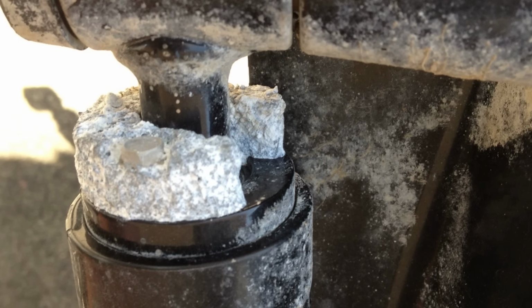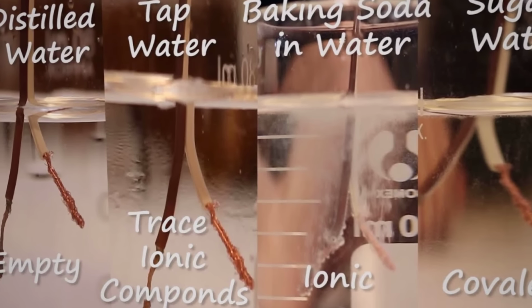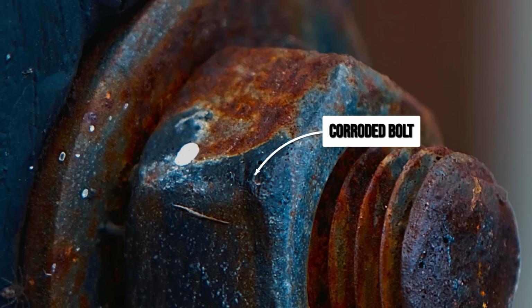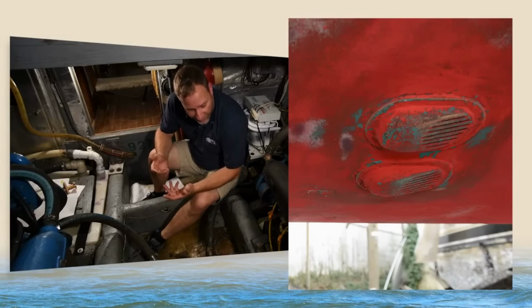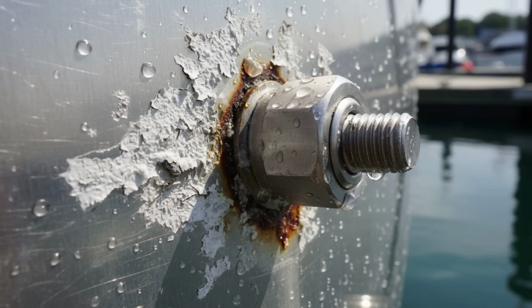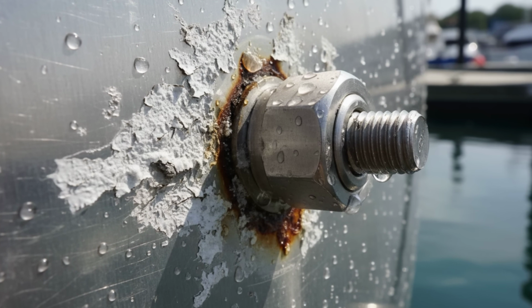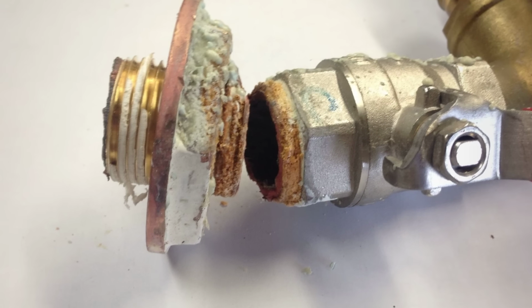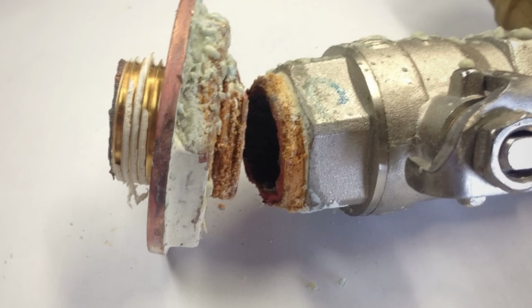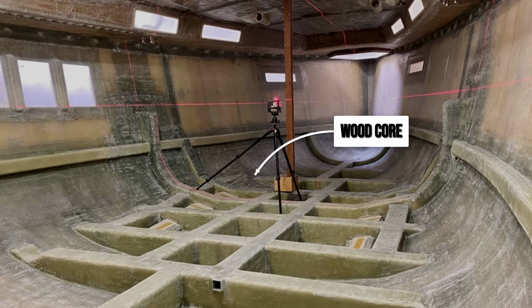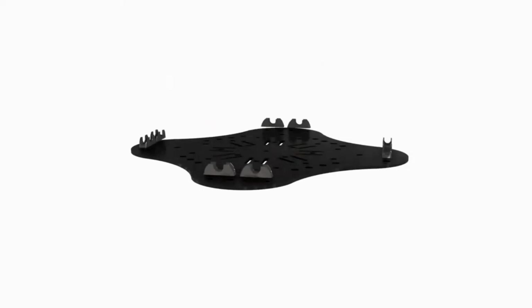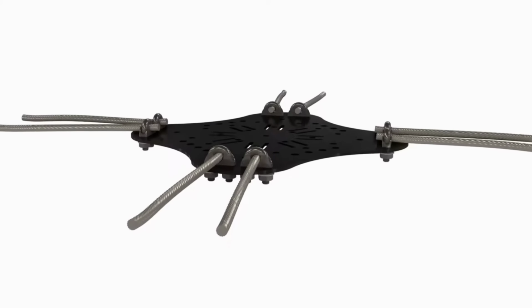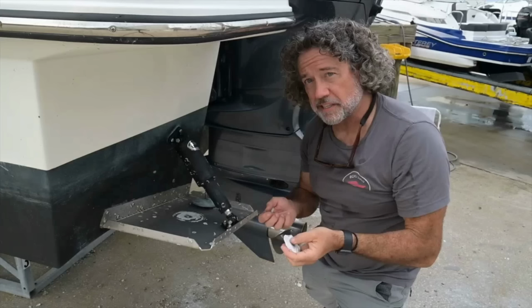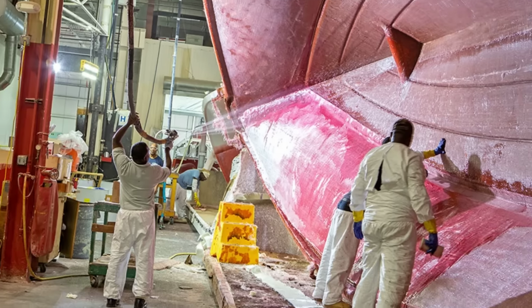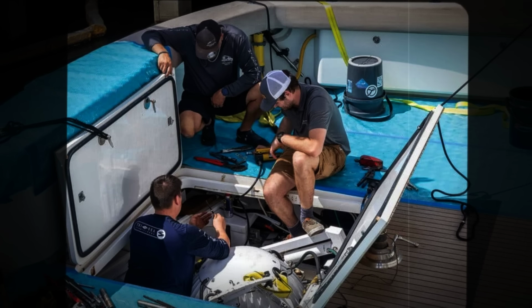The second is galvanic corrosion. Saltwater is an electrolyte. When 2 metals that sit at different positions on the galvanic scale are in direct contact and immersed in an electrolyte, the less noble metal gives up electrons and corrodes at an accelerated rate. On a boat, this means aluminum components corroding where they contact stainless steel hardware, bronze fittings pitting when not properly isolated, and structural mounting points failing from the inside before any visible surface deterioration appears. The boats that survive this environment isolate their dissimilar metals, use the correct alloy for each application, and maintain their zinc anodes. Most production boats are not built with this level of attention to the details a buyer cannot see on a dealer lot.